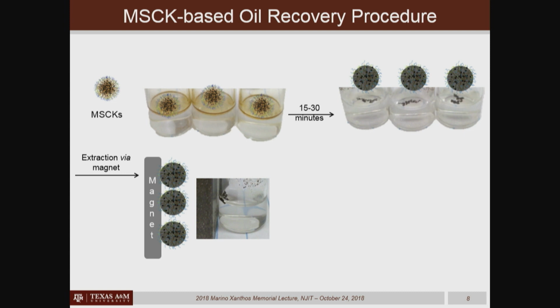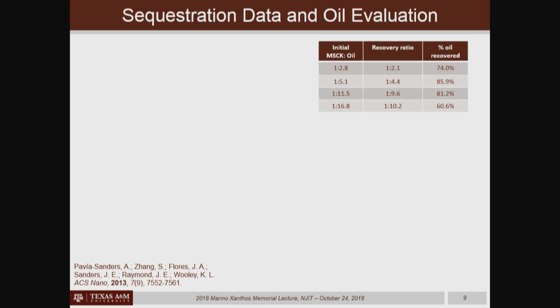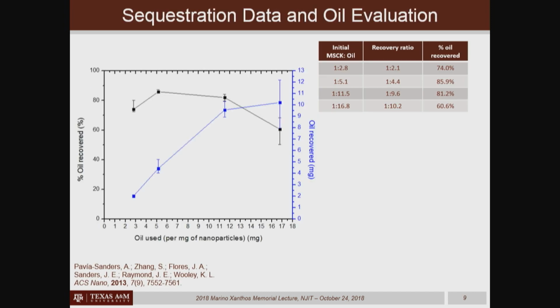And then when a magnet is placed next to the vial, those particles then migrate to the vial wall, and then the residual solution can be decanted and then extracted for chromatographic analysis of the remaining crude oil that was not collected by the particles. And so in the analyses here, let me just go through this quickly. Adriana always used an excess of crude oil. So she's using from about 3 milligrams of crude oil per milligram of nanoparticle up to almost 17 milligrams of crude oil per milligram of particle.